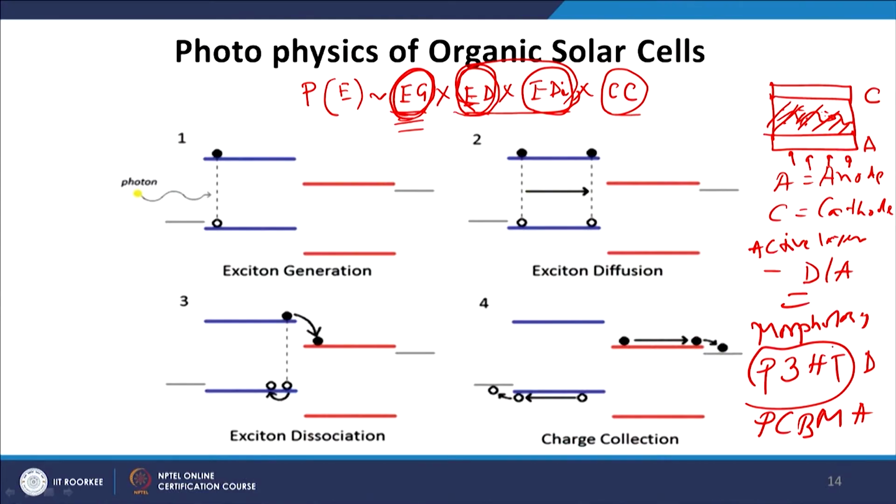Now, for example, P3HT is soluble in chloroform. So, chloroform is a solvent of P3HT, but if I take something like toluene, the solubility of P3HT in toluene is not good. So, we can say that toluene is an anti-solvent of P3HT, and you need to optimize parameters; it will be soluble, but in the beginning it will not be a very good solvent. So, now if I add toluene to the P3HT chloroform fabricated thin film during the spin coating process, the morphology will be different. So, depending upon the experimental parameters, the morphology of the films can be way different.